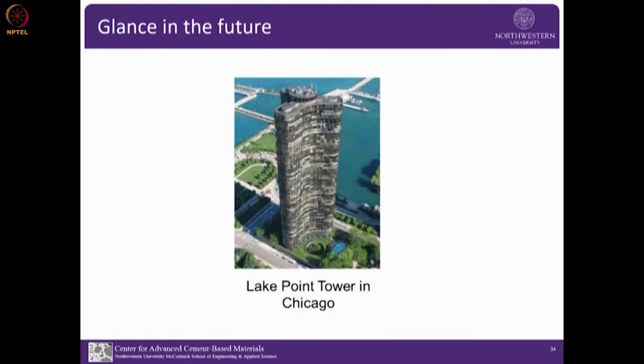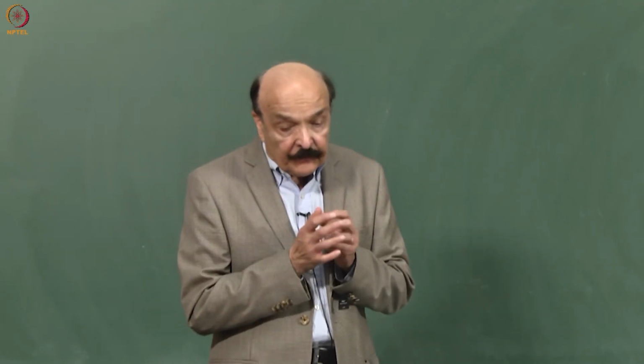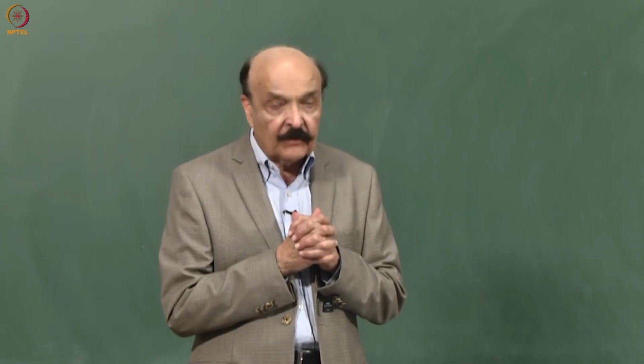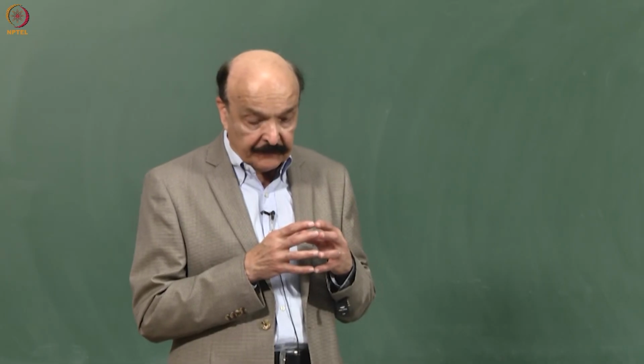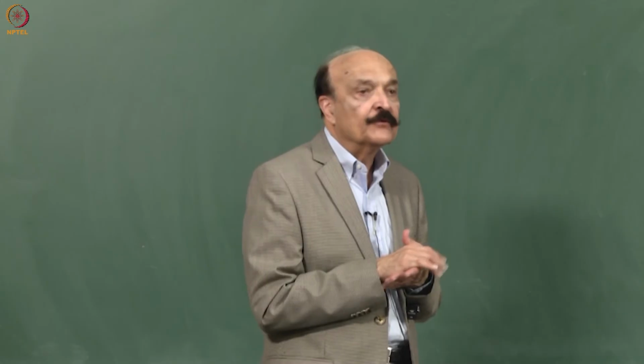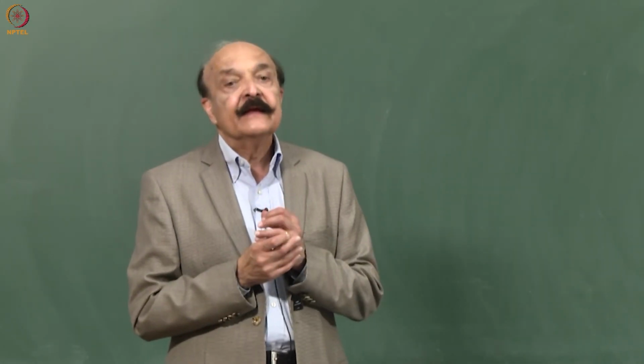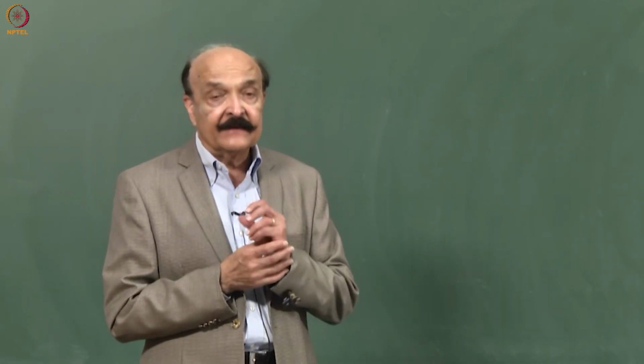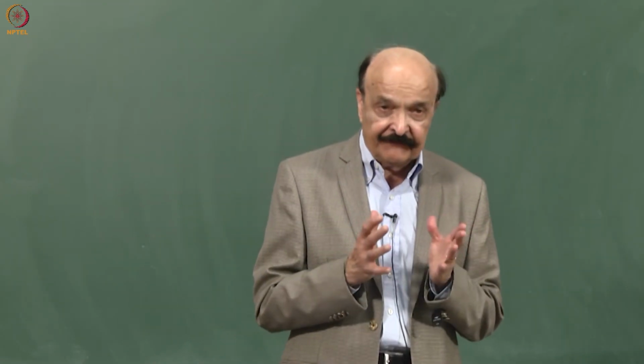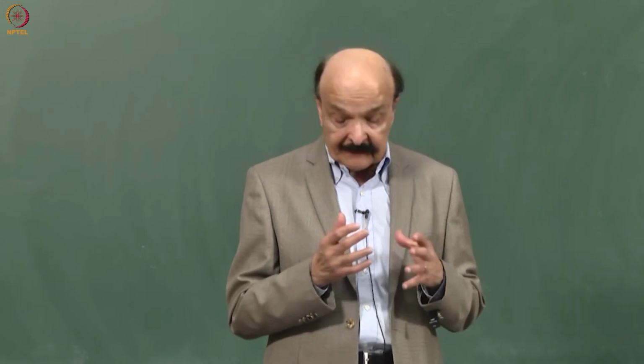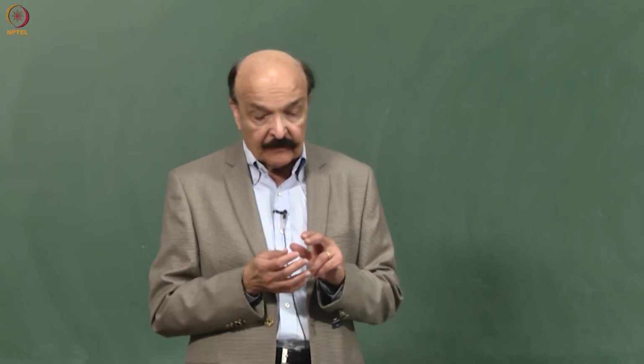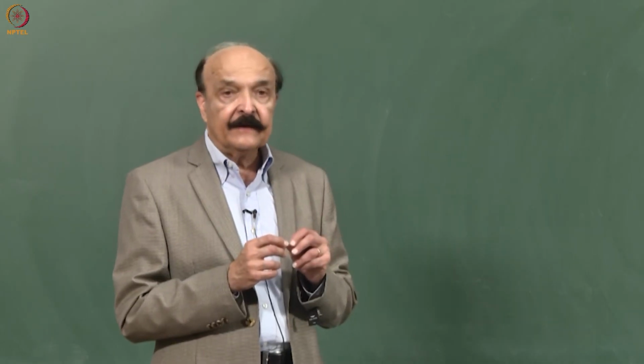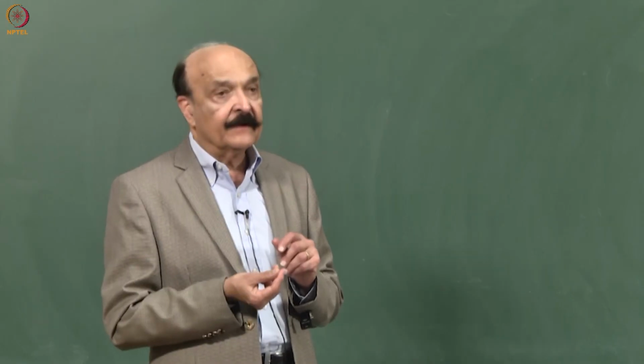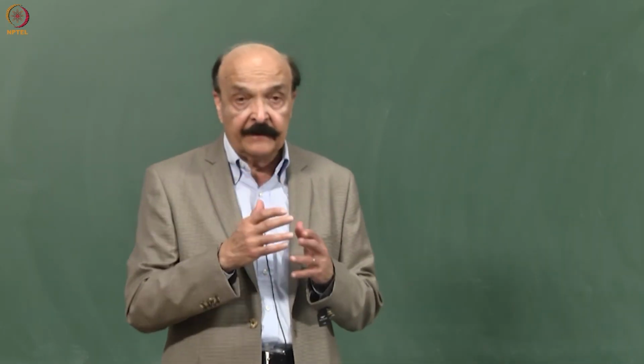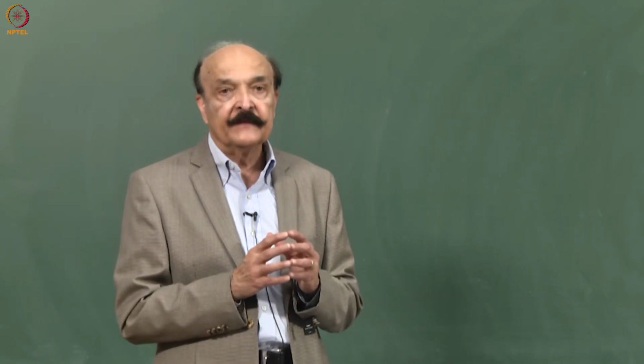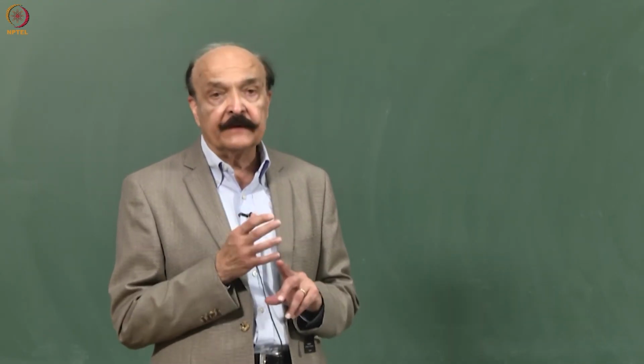Then I want to conclude with a very interesting direction. Last year, about January, a big ready-mix company, I think called Prairie, and before, when you were there, it was Material Service, now one of the largest, called a workshop. They said that tall building designers want to double the modulus of concrete. We are talking about 55 gigapascal. There were people from material suppliers, ready-mix, and contractors, and they said that currently, to satisfy the modulus requirement, they are increasing compressive strength. For a tall building where they would be happy with 100, they are using 140 just because of the modulus. That means more cement, which is not sustainable, and the material is also more brittle.